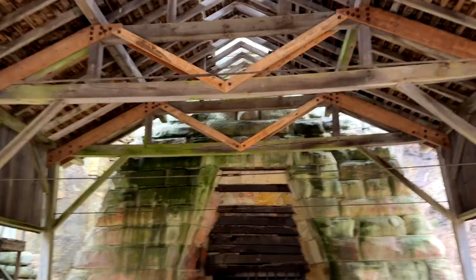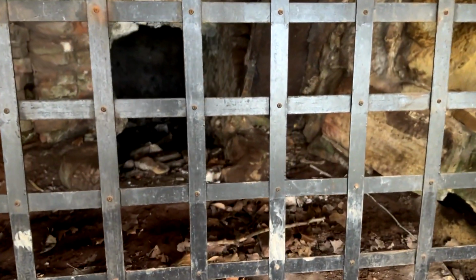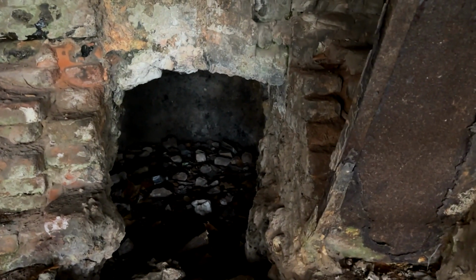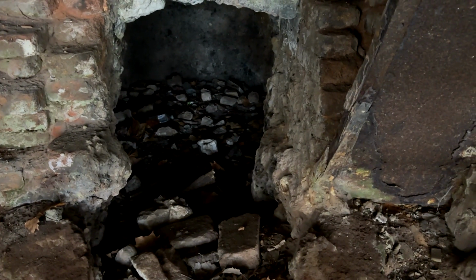All right, so here's the casting room. And we'll walk a little closer here to talk about what would happen. So after iron and slag settled, you would have guys that would wear leather aprons, some headgear, large leather gloves, come up to this area, and you'll notice there is some fire clay brick that lined the inside of the furnace. And so inside there would be some really hot stuff burning, and they would have a set of stone placed there purposefully to allow for slag to roll over top of it, and then a clay plug underneath that they would pop once the slag rolled off, and it would allow the iron to run down this little area and into this little sandy casting area.